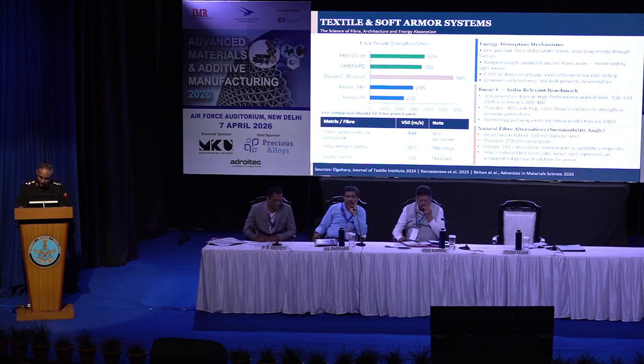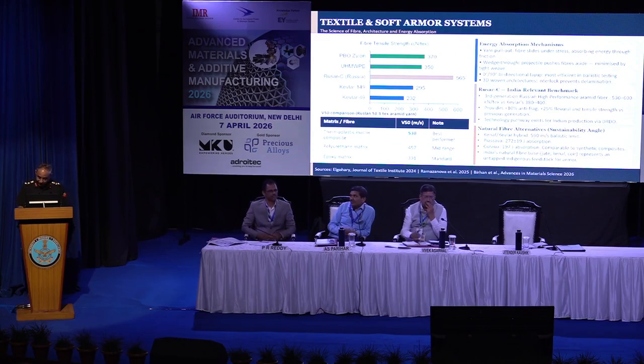The Rusar C, a Russian third generation high performance aramid fiber, at 565. See the difference. That is 2.5 times stronger than standard Kevlar. And let me tell you that DMSRDE Kanpur is working in this space. The requirement is to accelerate Indian fiber performance to this benchmark. The architecture matters as much as the fiber. A 90 and 0 degree bidirectional layup is consistently the most effective because fragments arrive from any direction. The fiber network must arrest motion in all directions simultaneously.